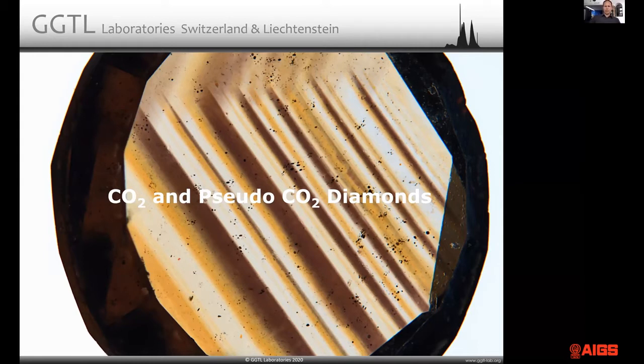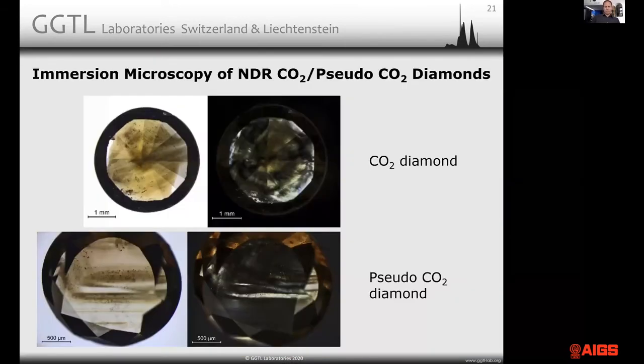There are so-called CO2 diamonds, and the class that I actually defined in 2003 as Pseudo CO2. The reason for Pseudo CO2 is they have exactly the same properties as CO2 diamonds, but don't show CO2. Now I'll show you where this CO2 can be seen in those diamonds. Let's look at the immersion first of all, so you see what's the difference between these and deformed brown diamonds. The most typical CO2 diamond shows the color distribution as you see on top. It's typically a color patch that's somewhat inhomogeneous, non-homogeneous in distribution.